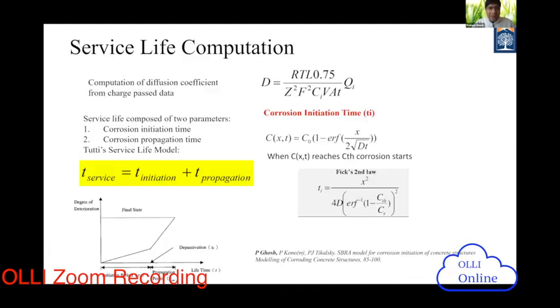And we talked about the service life. Basically we have two parts: one is initiation, the other one is propagation. We use different methodologies to get to diffusion from the charge passed. Basically the aim is diffusion. We apply the charge passed, we get the diffusion, we put it back in our equation to get our initiation time, and then you get the propagation time to get the total service life.